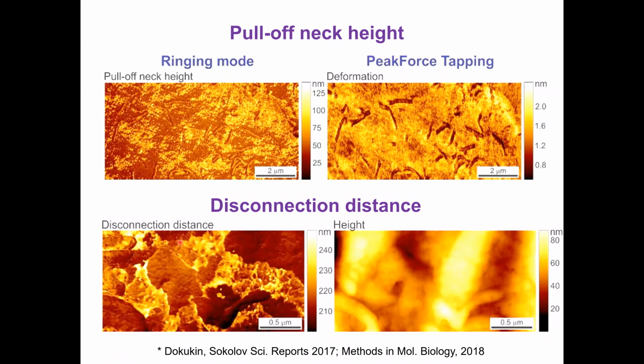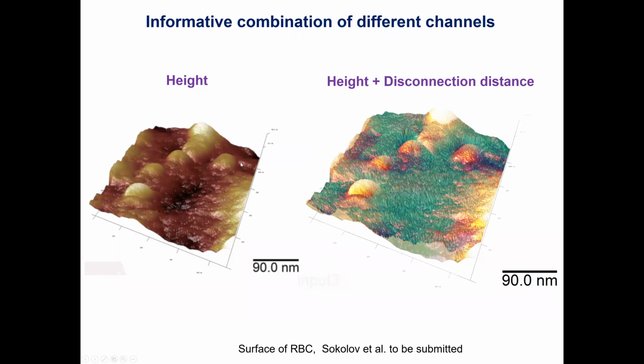Disconnection distance is the size of the molecules attached to the surface. Again, this is a height for reference, height recorded with peak force tapping, and this is disconnection distance. So you can see it's also patchy, and the size of this can get up to probably like 300 nanometers. So it's definitely something interesting and never was reported before, to the best of my knowledge.